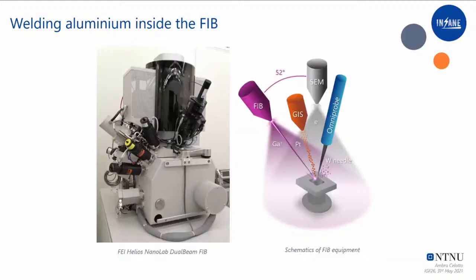I'm a PhD student at NTNU, and my main supervisor is Prof. Filippo Berto. The work I presented was about a method for cold welding of aluminum inside a FIB microscope. A FIB microscope is nothing more than a scanning electron microscope equipped with other tools that allow different procedures. First of all, we have a focused ion beam, which allows a different perspective by imaging the sample. It is also able to mill out material from the sample. Then we also have a gas injection system that allows chemical vapor deposition onto the sample. And above all, the most important for my work here, the OmniProbe needle, which is nothing more than a tungsten needle that allows us to manipulate small material pieces inside the chamber.